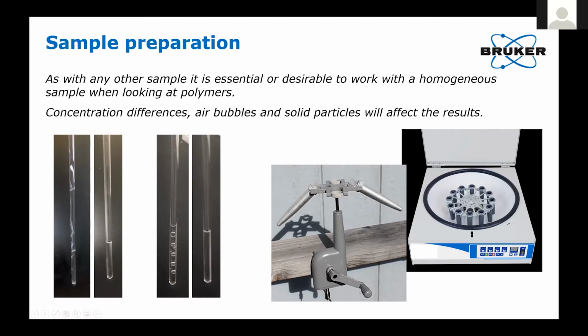Centrifuges are really helpful. And the hand crank centrifuge is a wonderful tool for almost any NMR spectroscopist, because you can effectively spin the viscous material to the bottom of the tube, or you can spin the solution to the bottom of the tube, and the air bubbles being lighter, they go up.